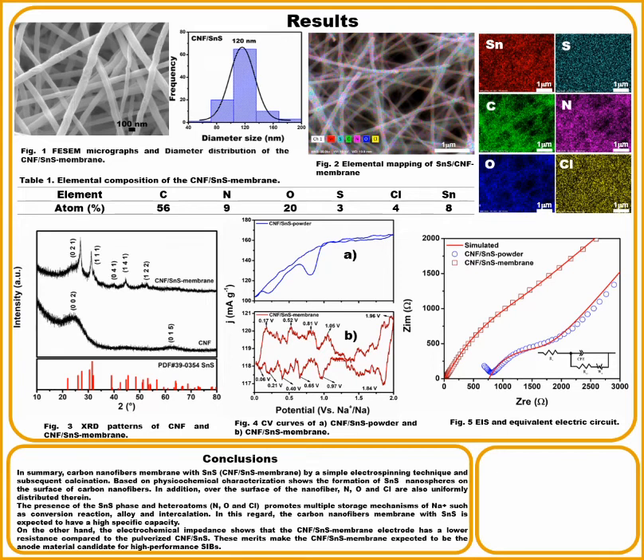Therefore, the carbon nanofiber membrane with tin sulfide is expected to have a high specific capacity. On the other hand, the electrochemical impedance shows that the carbon nanofiber membrane with tin sulfide electrode has a lower resistance compared to the pulverized one. These merits make the carbon nanofiber membrane with tin sulfide expected to be an anode material candidate for high-performance sodium-ion batteries.